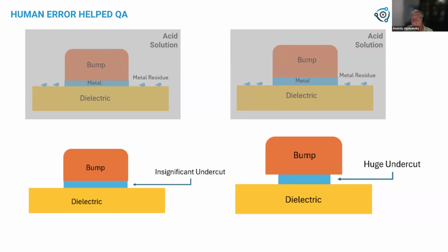And more than that, we found such undercut also on wafers with regular processing, and we improved it. We reduced concentration, we reduced temperature, and we improved it. This is the difference. So do you have questions? If I explained it clearly, I think it's a good example.